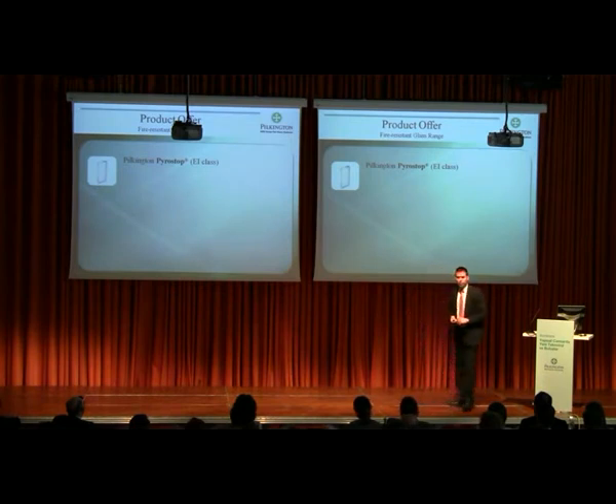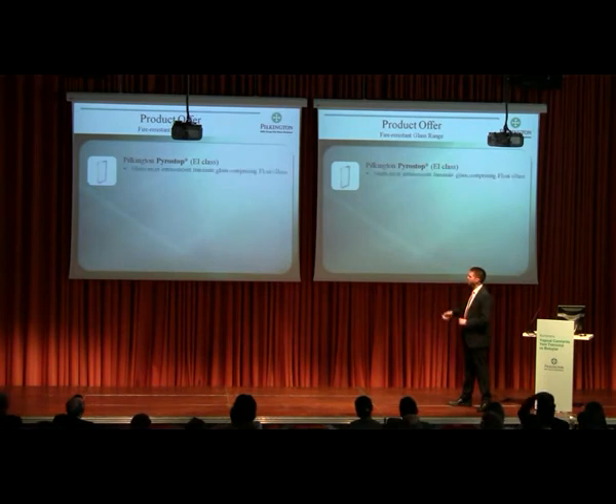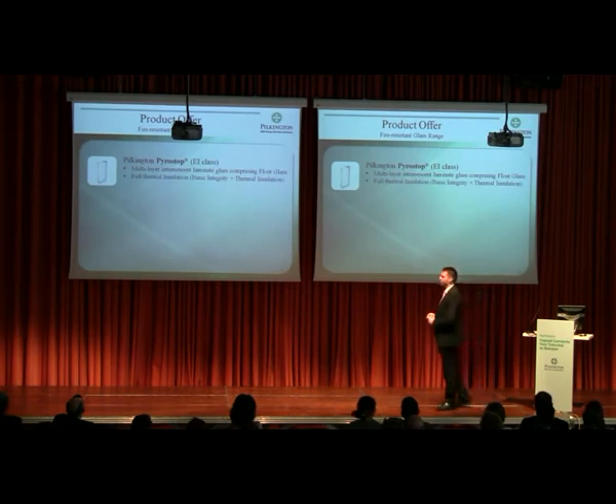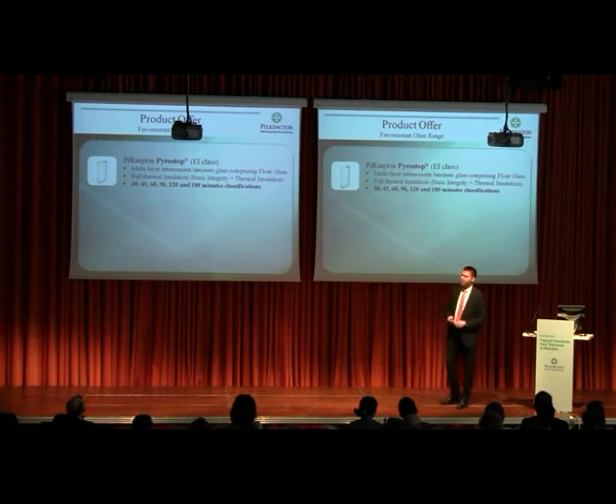Okay, let's summarize the product range we can offer. Looking at Pyrostop for insulation and integrity: multi-layer intumescent glass comprising float glass. Full thermal insulation means basic integrity plus thermal insulation. Available for 30 minutes, 45 minutes, 60 minutes, 90 minutes, 120 minutes, up to 180 minutes. Just to give you some impression, the 30 minute type is 50 millimeters thick.